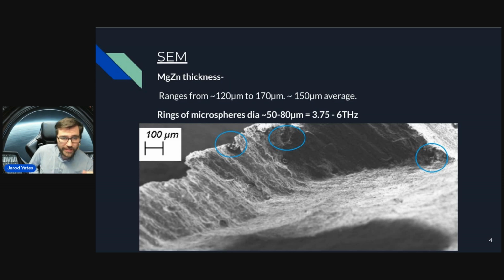In that I saw some thickness measurements of magnesium layers, and I now feel more confident about what the thicknesses of these layers are. I would say it's about 150 micron average layer for the magnesium zinc layers. Also, an important takeaway is there are these rings of the microspheres that rupture.